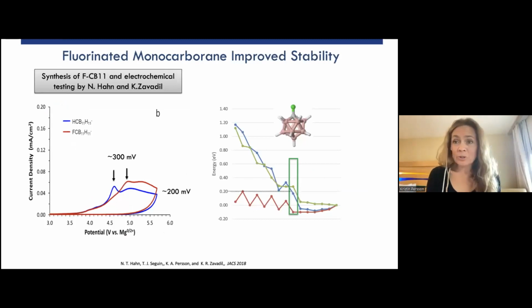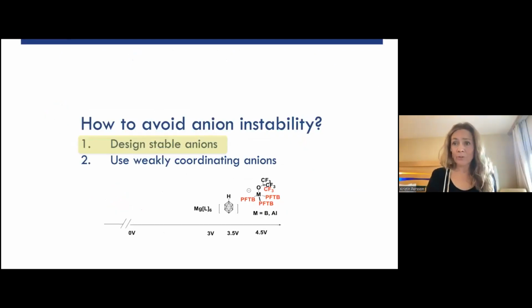Okay, so does it do better in terms of anodic stability? Yes, again, fairly modest, but the response is there, about 200 to 300 millivolts of an improvement compared to the existing monocarborane. And this was similar to what we computed from first principles. Okay, so that's one way of trying to design novel anions that, even when they're contact ion paired with the multivalent cation like magnesium, withstand this really difficult intermediate charge state.